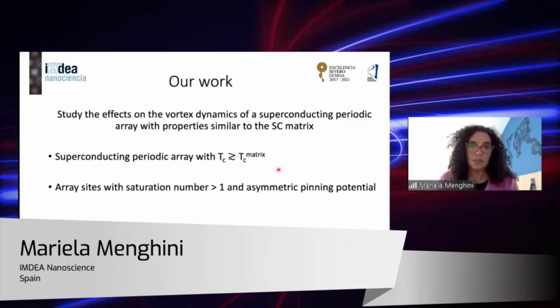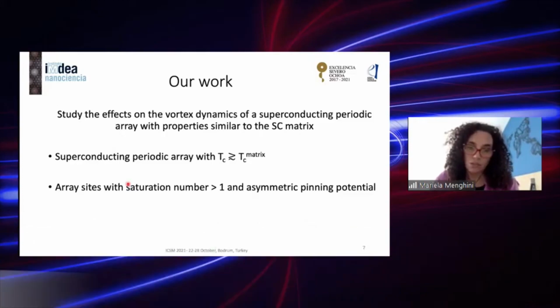In our case, we want to study the effects on vortex dynamics of a superconducting periodic array with properties that are similar to the superconducting matrix. For this, we chose a periodic array of superconducting nanostructures with a critical temperature only slightly larger than the superconducting matrix. And we have chosen array sites, these nanostructures, with a saturation number such that they can allocate more than one vortex, right? So the saturation number is larger than one, and actually they will form an asymmetric pinning potential.